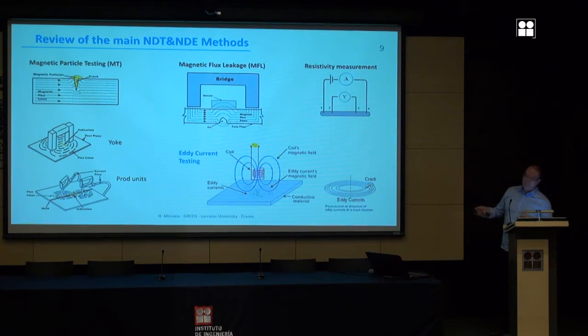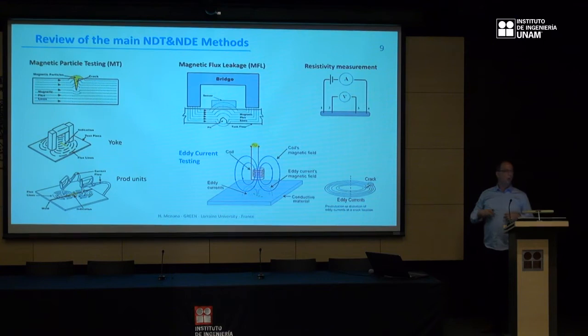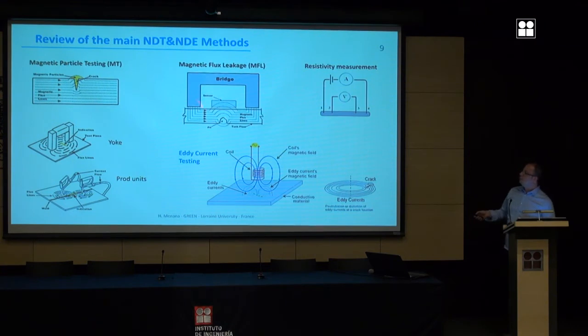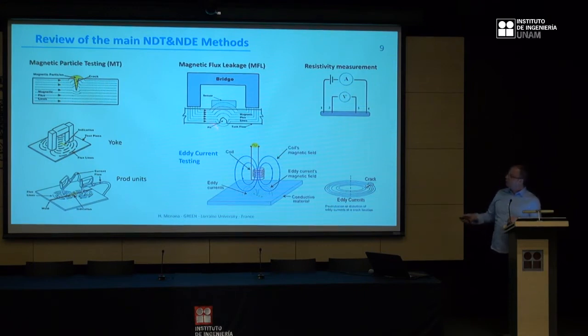The first method here, magnetic particle testing, concerns external flaws or cracks. When it concerns buried flaws, internal flaws, you can use what we call the magnetic flux leakage method. It concerns magnetic, ferromagnetic material. You magnetize the material by applying a magnetic field with a yoke, and then with a Hall sensor, you can detect a flux leakage due to the presence of flaws. This is called magnetic flux leakage inspection.